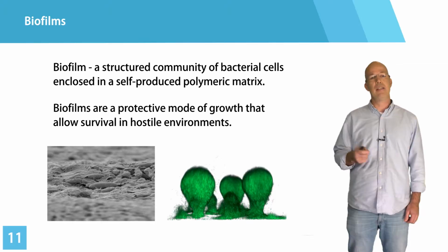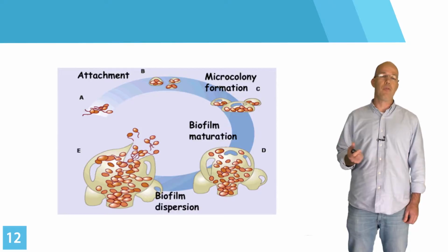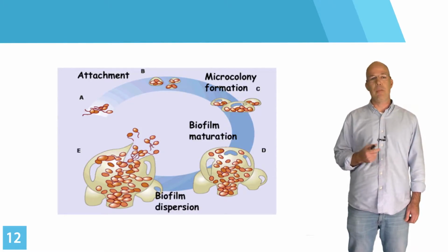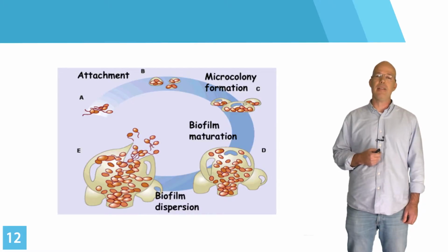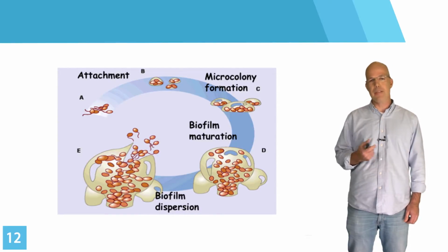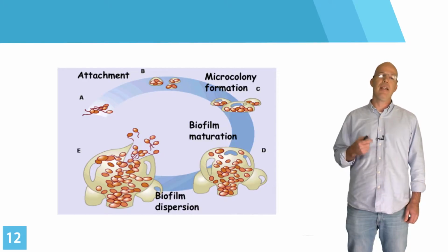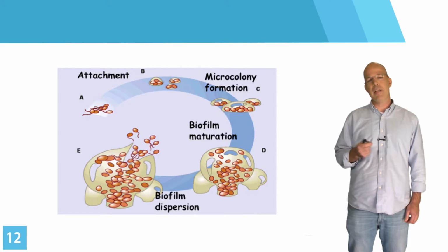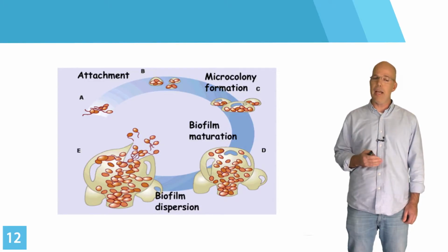This could be UV, heat, and also antimicrobial activity. And how are biofilms formed? It happens very quickly. Bacteria, which are about a micron in size, can bind a surface within minutes, and in the beginning state the binding is reversible. Bacteria will move on the surface, but after a few minutes to a few hours, they become irreversibly attached. They start multiplying, form microcolonies, secrete the matrix, and in a few days you get a biofilm that is fully mature and growing.